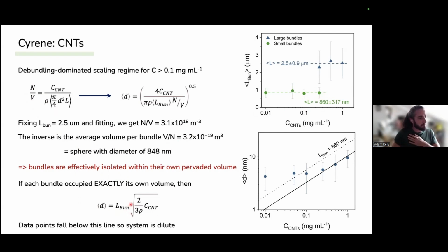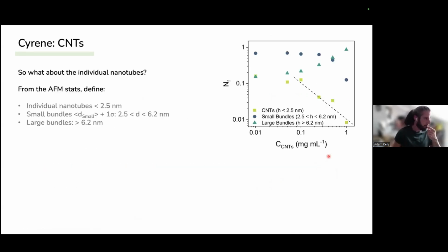So by setting the length of the bundle to be 860, we get this dotted line. And the fact that our data points lie below this line means that our system is dilute. So the small nanotube bundles are not in contact with each other. But this doesn't tell us much about individual nanotubes.